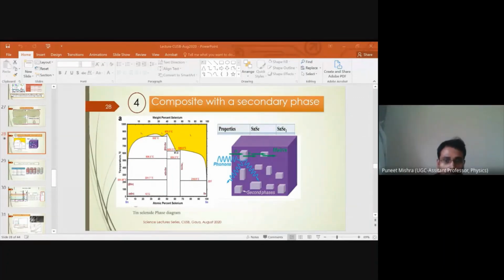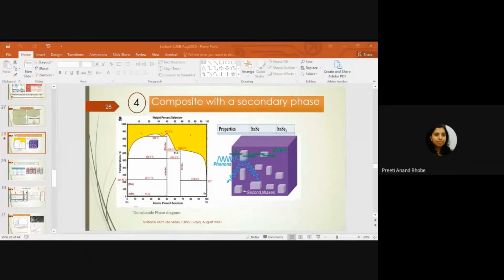Dr. Pawan Kumar wants to ask, what was the particle size of SnSe2? For SnSe and SnSe2, these are polycrystalline materials, and it's not possible to measure the size. You will have SnSe and SnSe2, which will look similar in your SEM image. You cannot distinguish the two in an SEM. Maybe if I did a TEM, I would know that I have a region with a certain lattice constant compared to another region with a different lattice constant. But I could not determine the particle size that way.